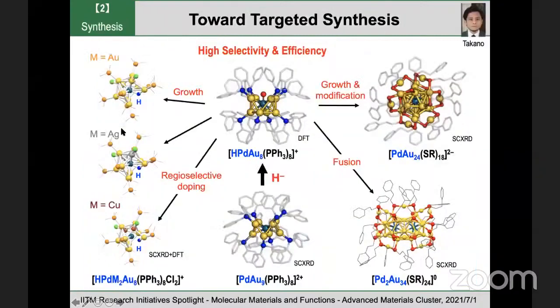Our first project is the development of a new synthetic method for new superatoms in high yield. We recently found that hydride, H-, doping of some superatoms can induce a variety of chemical transformations, such as core growth, regioselective doping of other elements, and surface modification with different ligands. And we recently found that two superatoms can fuse into a dimer of superatoms by this approach.